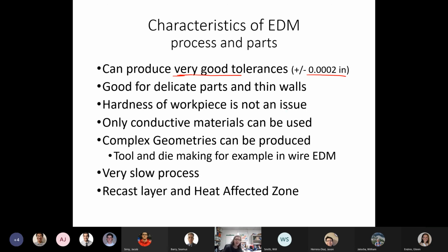Hardness of the workpiece is not an issue. So this is a process that for our really high hardness materials, our hardened steels, works very well. We are limited to only conductive materials. So we cannot do EDM on plastics, on ceramics, and many composites unless it's a conductive composite. We can do very complex geometries.